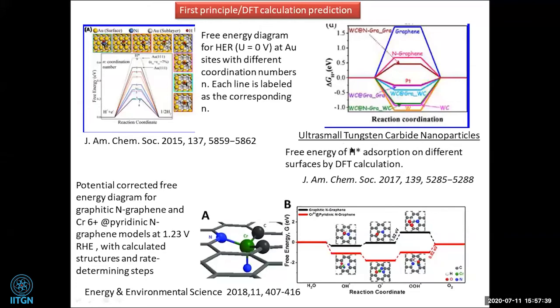Another example is the ultra small tungsten carbide nanoparticle. Again, same description here. One more important thing: in this one, graphitic graphene and chromium doped. When chromium is doped, you can see the energy is minimum for these hydroxyl groups. So where we have the minimum free energy, that is ΔG. So we come to know that when we have a preferred material, a preferred size, that gives us the minimum potential, minimum energy for hydrogen adsorption and hydrogen desorption, that gives us good hydrogen evolution reaction.